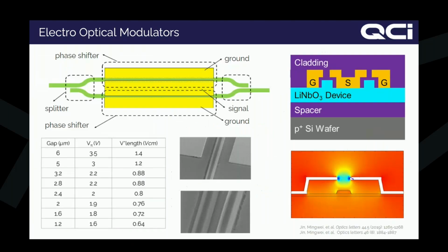applications such as that. The electro-optic modulators that we have demonstrated, one key element of them is the V-pi value that you can get, and as you can see here in different publications, we have shown that we can get V-pis as low as 1.6 volts, and that's very good because you need a low V-pi to be able to drive the modulator with current DSP formats. It's very important for this voltage to be low because DSPs need to be operating at lower power, therefore saving a lot of power and energy for the overall system. So that's why thin film lithium niobate is an important material, because of the low V-pi that we can get.